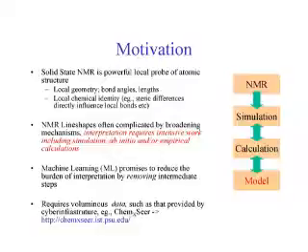So what motivates us? Well, we have this great powerful tool, this local probe, which looks at the angstrom and nanoscale of materials. It can reveal things like bond angles and lengths and chemical identity. But in the solid state, we have the pernicious influence of broadening mechanisms and interactions which can complicate interpretation. So interpretation in solid-state physics and chemistry always is supported by some form of approximate calculation or ab initio or first principles calculation, as well as the need to simulate this spectra.